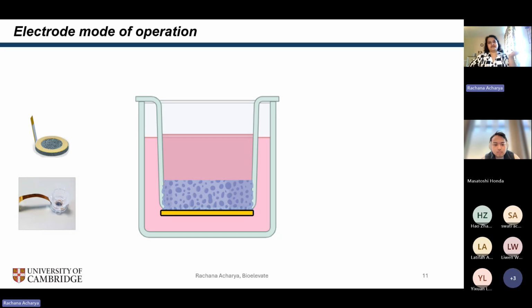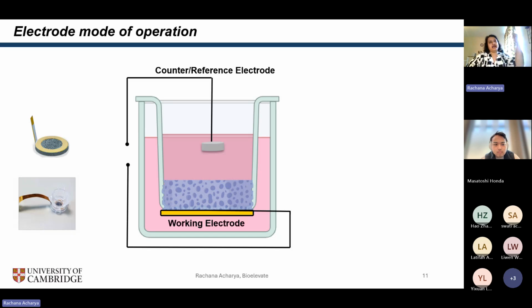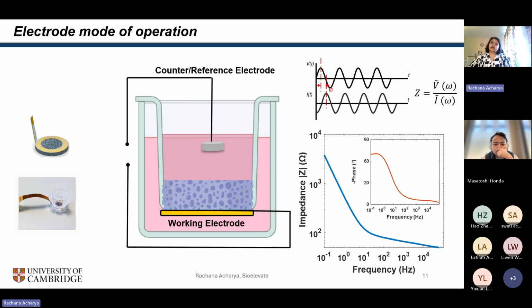So let's see what kind of devices we can make. If I contact the scaffold with a gold electrode on the bottom, and then I have a counter reference electrode on top, I can operate this device in the electrode mode of operation, and I can perform a process called electrochemical impedance spectroscopy. For those of you who are not aware, we are applying a small signal AC voltage, measuring the current, and then calculating the impedance of the system as a function of the frequency of the AC signal.